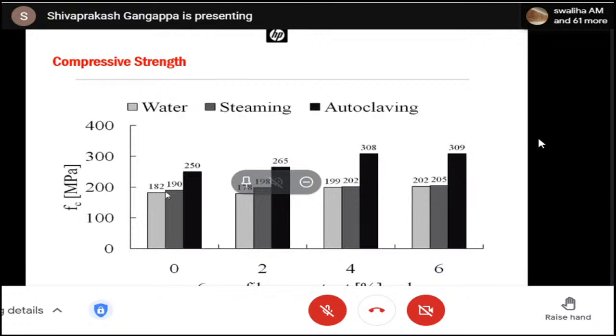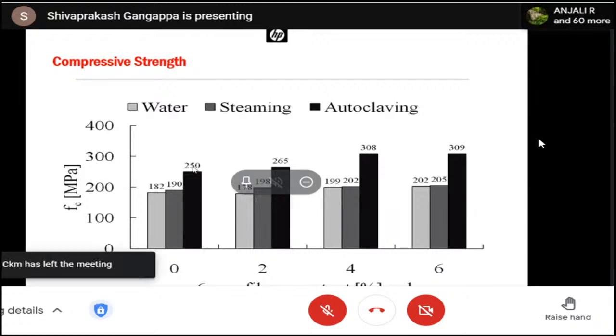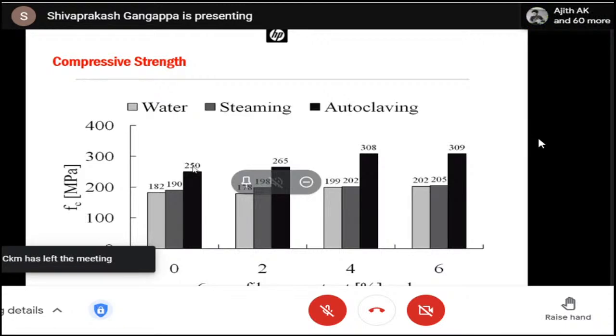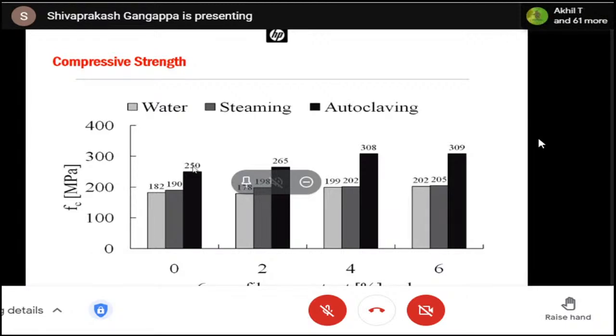But the cubes kept in the oven for about 2 days show a drastic increase in compressive strength to 250. These 250 are megapascals, means to say Newton per millimeter square. Can we produce a concrete of 250? Yes, definitely we can produce.